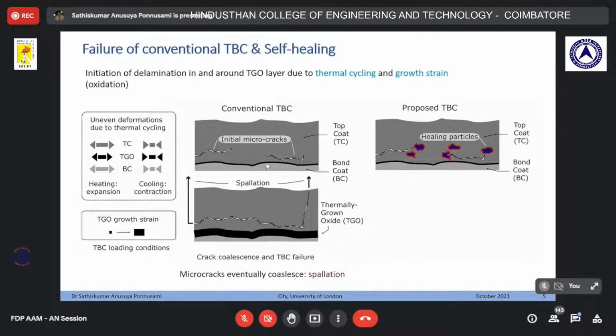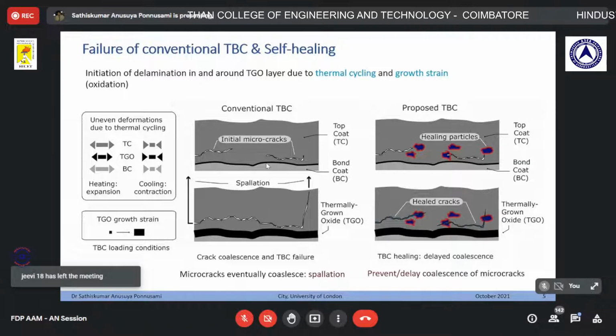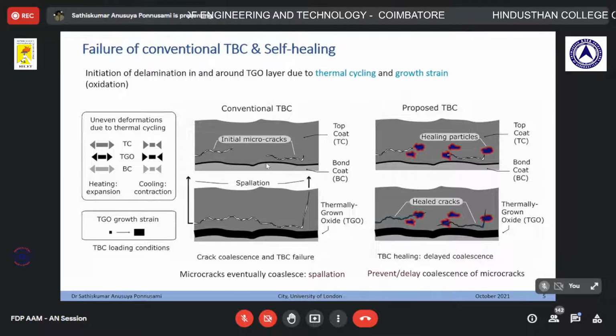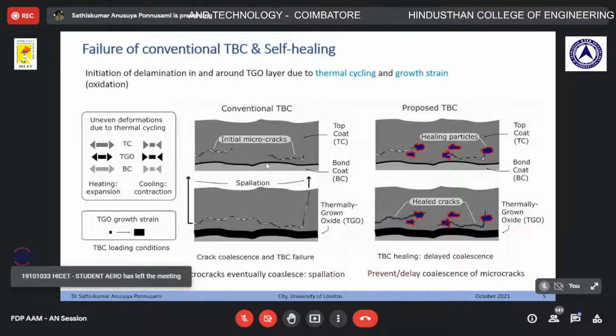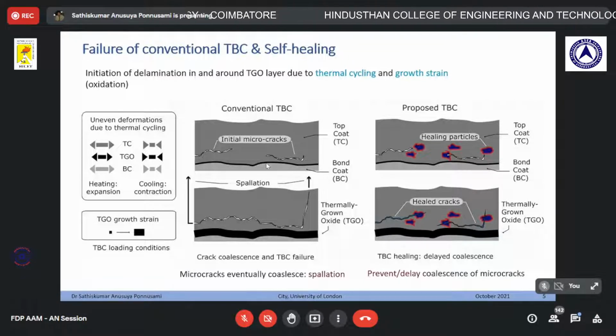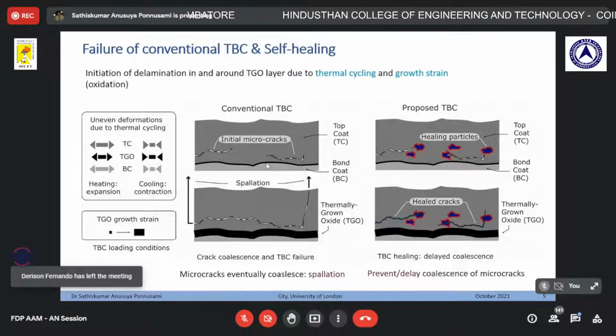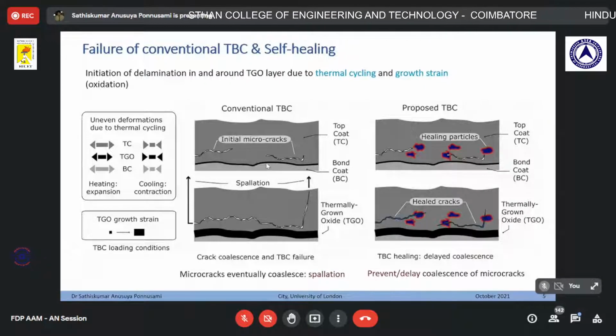Okay. So what you are effectively doing is that you see the blue-colored healed cracks. You are not allowing the micro cracks to coalesce, meaning to join together to form a major crack, as you see on the left. Remember, the important point here is you are not preventing any crack from forming, because that is unavoidable. Cracks do form, but what we are trying to do is heal all those little micro cracks and prevent the formation of a major crack. And by doing it, you basically enhance the lifetime.